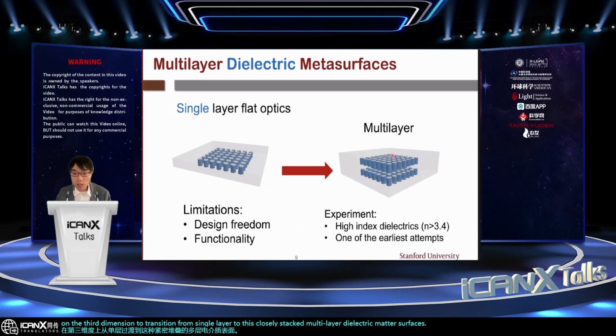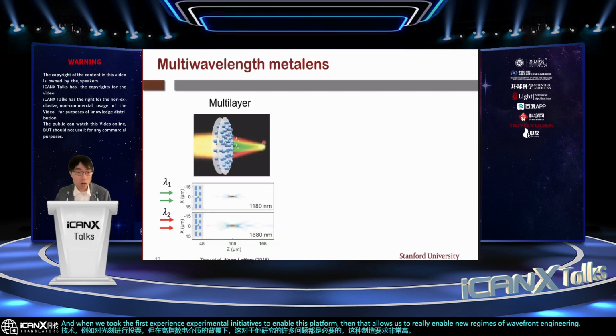The critical challenge of this platform is the fabrication. And it's worth noting that the 3D processing of low index polymer has been well established. We can use techniques such as two-photon lithography, but in the context of high index dielectrics, which is necessary for many metasurface studies, this fabrication is very demanding. So we took the first experimental initiatives to enable this platform, and that allows us to really enable new regimes of wavefront engineering. Based on our platform, we first tested its capability in the context of metalenses.